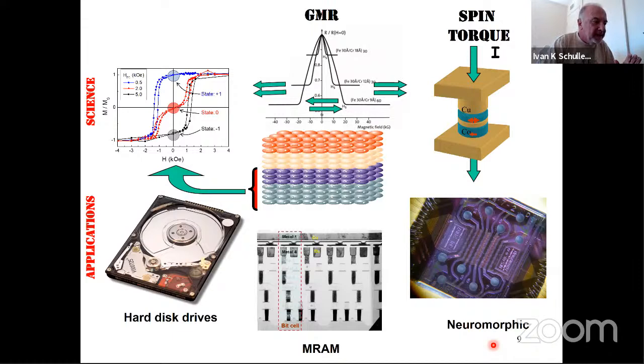Here I am plotting the magnetization as a function of magnetic field for this bilayer of these two materials. The reason this is interesting is that this bilayer does a very strange thing. Sometimes the magnetic hysteresis loop, M versus H, is shifted to negative values. Sometimes it's shifted to positive values. And sometimes there are even two steps in one single magnetic material. That is all related to what happens here at this interface, and that's what I want to tell you about today. That gives you the motivation of why one wants to work on two materials in proximity: they do something different from what they would do if they were alone.